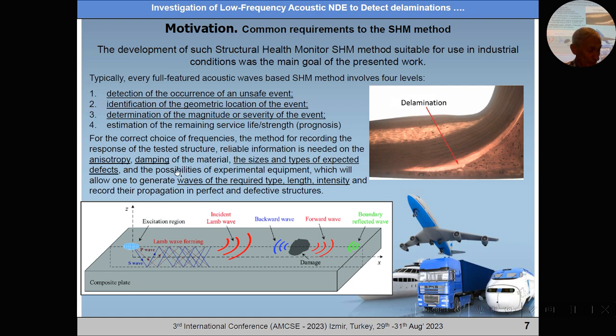Experience gained by world-leading manufacturers of composite parts shows that the most common defects are separation of adjacent layers inside composite laminates, formed during cure due to residual air or evaporation of volatile substances in the resin. Known non-destructive evaluation methods include analysis of natural vibration modes, acoustic emission, shadow moiré interferometry, infrared, radiographic, microwave, and X-ray tomography. However, these methods are useful only in laboratory conditions, not at the manufacturer. In manufacturing, acoustic methods are most useful.